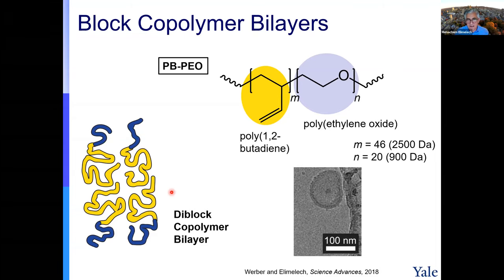And indeed, when we did this, we formed these vesicles and did cryo-TEM. You see that we can form a vesicle about 100 nanometers in size, with a thickness of less than 10 nanometers for the polymer that we've used here. So this is one of them that we were able to do.